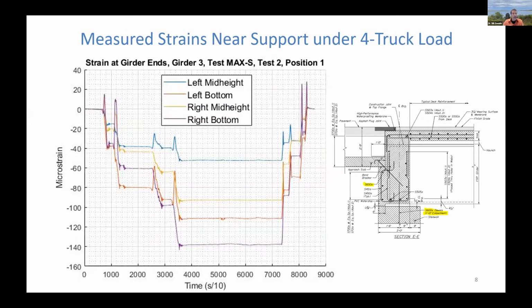So this is that same girder 3 in the same test, and these are strains measured at the bottom and mid-height of that girder at both ends of that girder. And we can see that we're getting significant negative flexural strains. That implies that we've got some negative moments at the end of the girder.